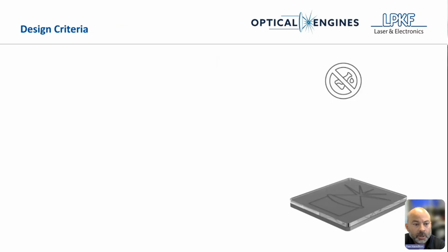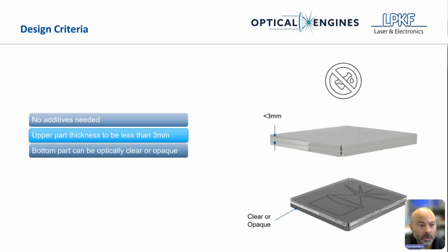All right, let's look at some of the design criteria. I'll jump into these because obviously the animation didn't work well. You don't need additives. The upper part thickness, so the first layer that the laser shines through, should be less than about 3 millimeters. This is kind of debated over the years, depending upon the laser power and the energy density of the laser, so it depends on the beam shaping. If it's truly Gaussian, we probably have to be a little less than 3 millimeters, maybe in the range of 1 to 2. But with the new top hat profiles that Optical Engines has in their lasers, we're actually able to get through a little bit thicker materials without burning that top layer. But still generally recommended that it's under 3 millimeters. And again, as I mentioned briefly before, the bottom part can be optically clear or opaque.